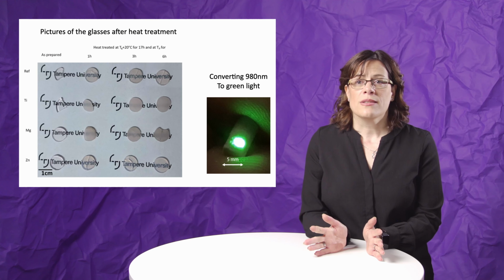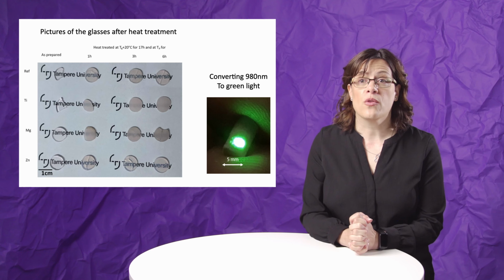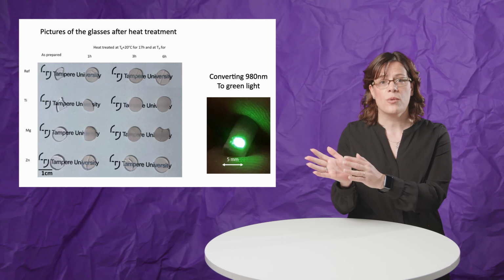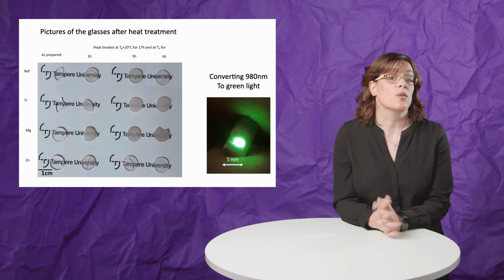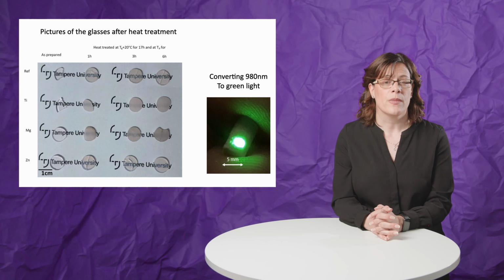Therefore, developing new promising glass ceramics is challenging, as not all glasses can be prepared into transparent glass ceramics. Nonetheless, we successfully developed transparent oxyfluoride glass ceramics with volume precipitation of erbium-doped calcium fluoride crystals. These glass ceramics are very promising as upconverter. They convert the near-infrared into visible light, green light, for example.